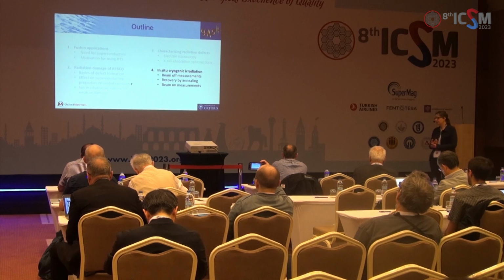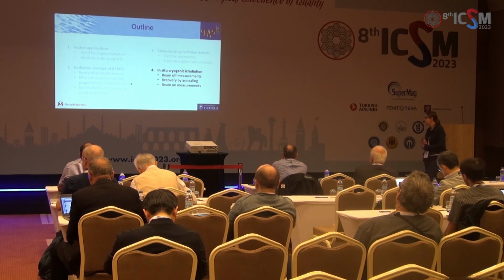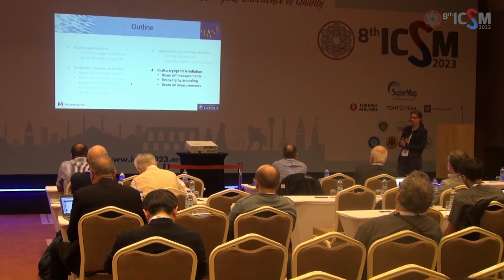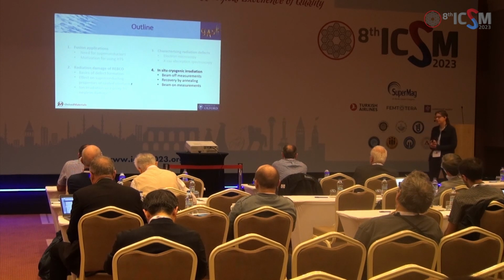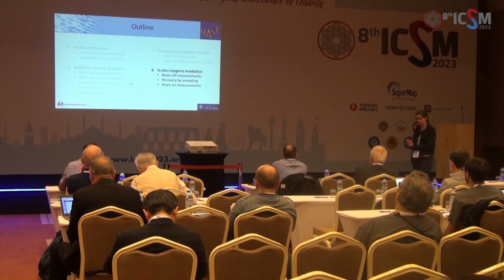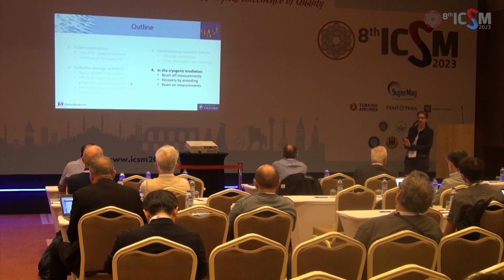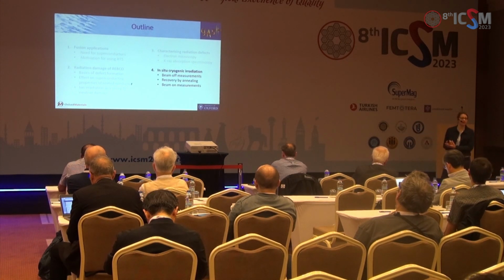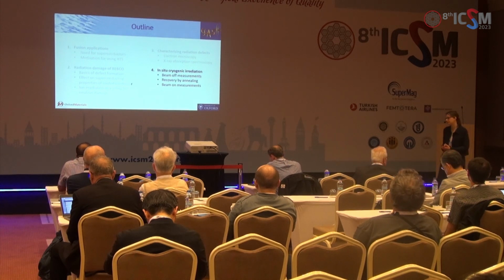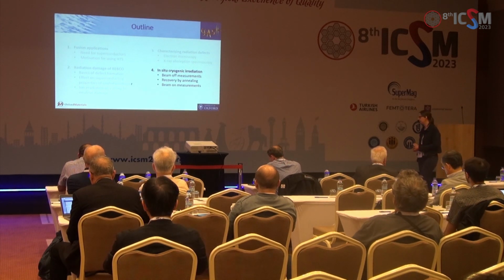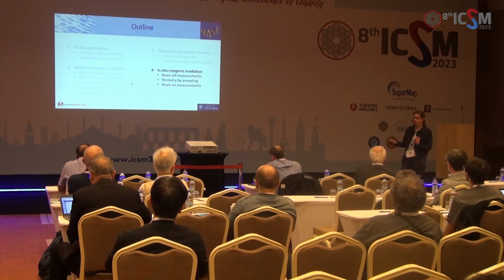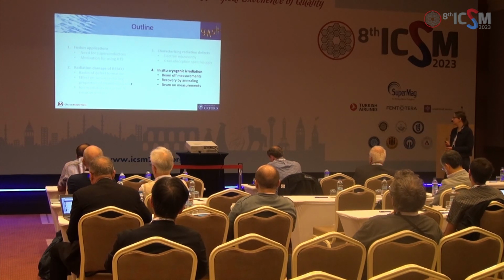Okay, so I'll move on to the final part of the talk, and this is some in situ cryogenic irradiation. Of course, all of the irradiation you've seen so far has been done at room temperature or slightly above. And in operation in our fusion magnet, the superconductor is going to be at 20 Kelvin or that kind of temperature. And we were interested in how that affected the defect creation in these materials and the superconducting properties.